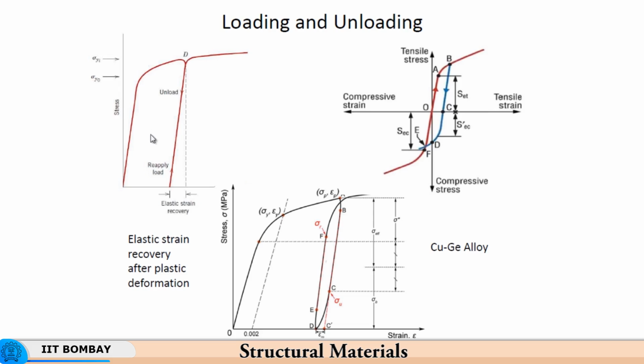Now, in some of the alloys like copper germanium alloy, when you unload a material, it shows a negative. Here you see that the strain recovery is much higher than what would have happened if the recovery were purely elastic. So, it is not just the elastic strains which have been recovered, but there is some additional recovery, and so you have this closed loop.